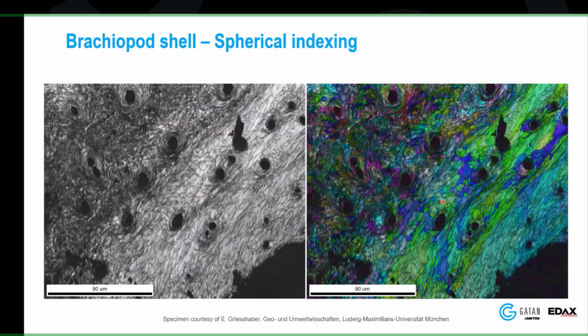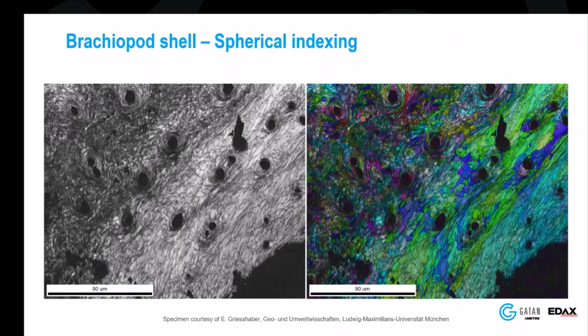So these new things like NPAR and spherical indexing allowed us to really do things. In this case, the main issue with this sample was that we had relatively low beam currents because it's biological material. Biological materials can't take much beam current without getting damaged. So there's little information, but because of these newer techniques, we're able to do this.